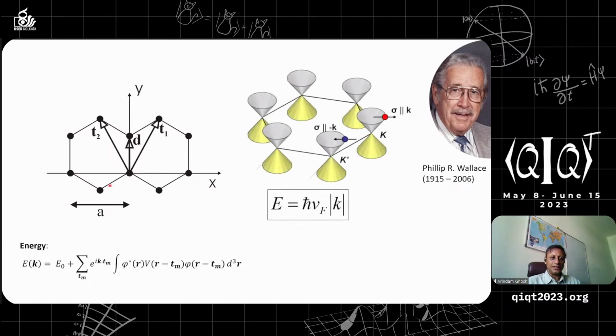systems. For example, in the case of graphene, if you simply take a tight binding model on a hexagonal lattice, and you take the p orbital pi electrons, because those are the low energy electrons that are available for most electrical and other physical properties of graphene, you will see that simply solving the tight binding model gives you the energy eigenvalues directly proportional to the momentum k, which means that at every point of this hexagonal Brillouin zone of graphene, you have the energy of the electrons varying linearly.